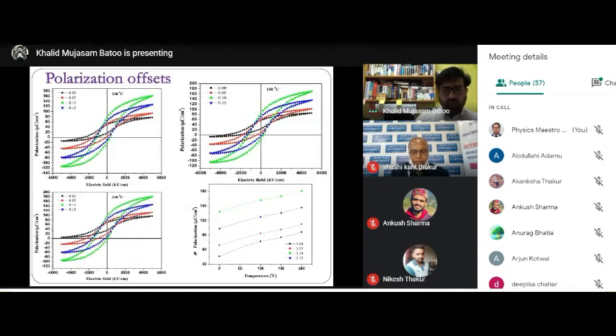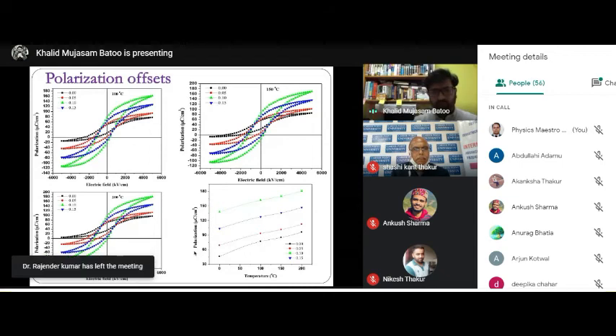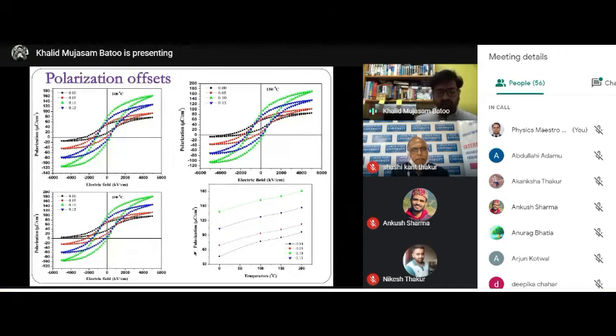What we saw further, we tried to hit the bottom of the layer - I mean to say, we tried to hit the substrate. And as the substrate was being hit, at the same time we used to measure PE again. So the loop was shifting from the negative side to the positive side.